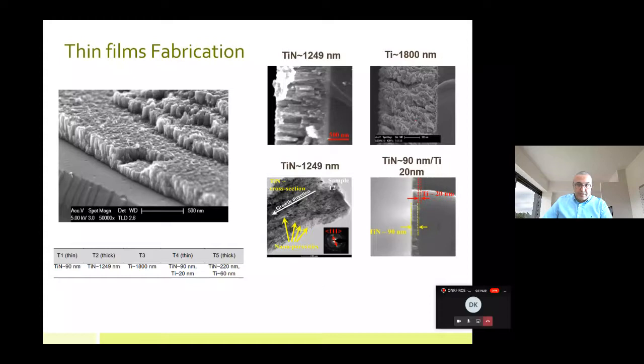Now, I must confess that while we were working on this project, the processing was still being evolved. As you can see, some of these pores are visible. So the corrosion response that we were able to achieve was with these defects in mind. And that basically would qualify some of the conclusions that I'm going to make.